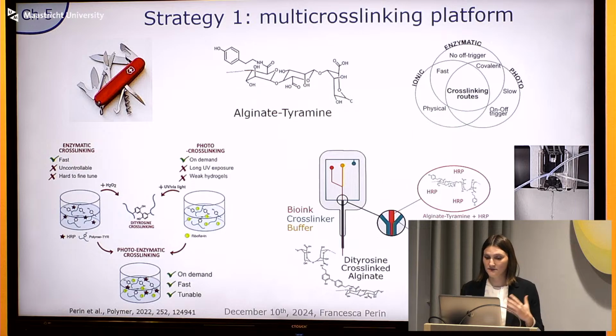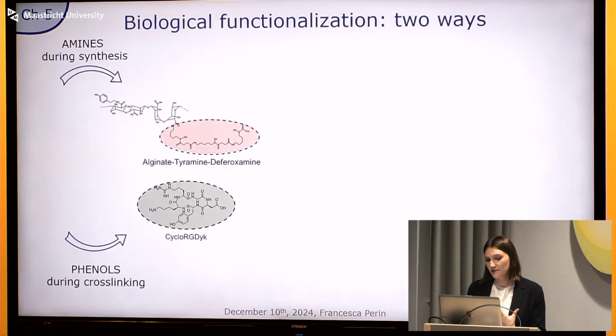Now that we had an ink and we could form it, we had to work on the biology, because alginate, as we know, is bioinert. So we need to give it something that the cells will like. And we did this in chapter 5, and we envisioned to do it in 2 different ways. The first one is for any molecule containing amines. We can graft them the same way that we grafted tyramine to the alginate, so during synthesis. And then any molecule containing a phenol can be added during enzymatic or photo-cross-linking via dityrosine bonding.